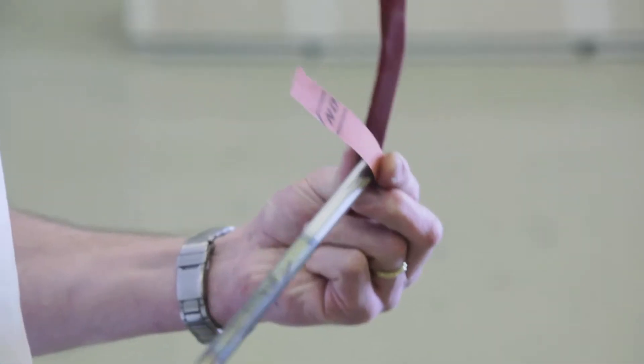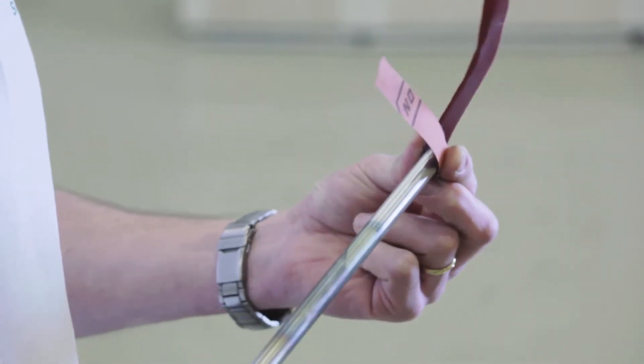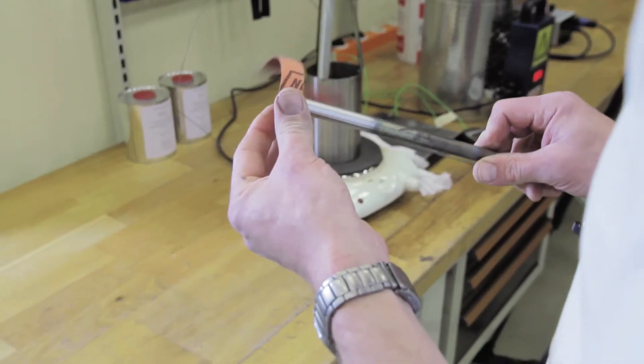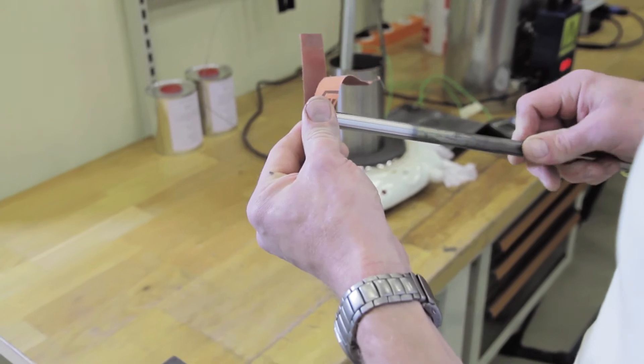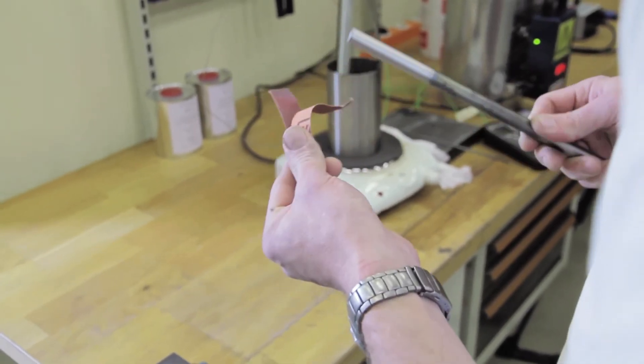Do not touch the grinded surface to avoid getting dust or grease on it because this can influence the cooling curve and how the vapor phase breaks. Check your grinding result carefully.